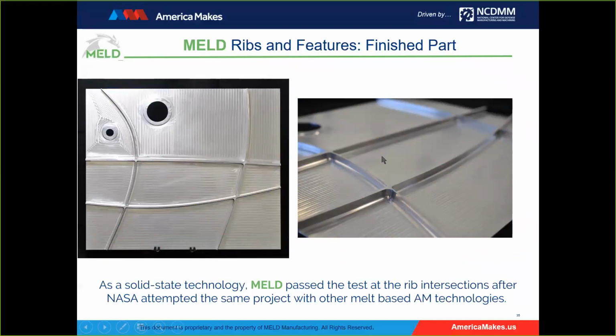We've done this with other additive manufacturing technologies that melt their feedstock. You're the first technology to pass this test with no mechanical property issues at that rib intersection. We found a technology that would allow us to print ribs onto this airframe. And of course, we've been singing Kumbaya ever since because NASA has turned out to be a valuable partner. They adopted friction stir welding two decades ago, back in 1991, and put friction stir welding on the map. And we're seeing the same type of relationship with NASA, and we're hoping they put us on the map big time like they did friction stir welding.